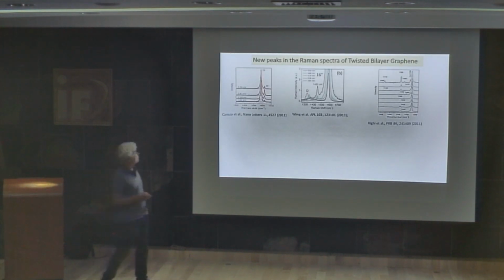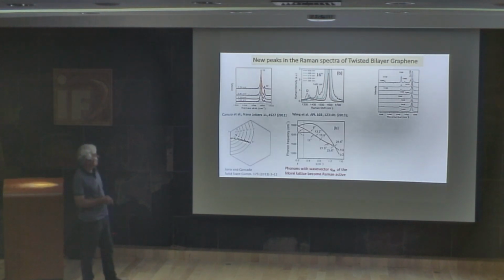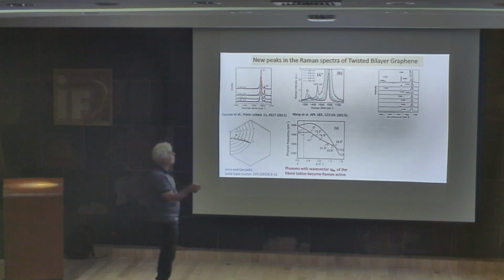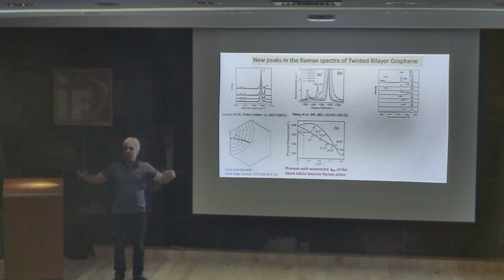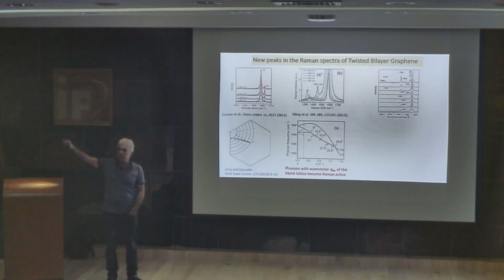And another important work that was done, and there is Jessica Campos who worked on this problem, was new peaks that appear in the Raman spectrum of twisted bilayer graphene. The point is that when I have the superstructure, the reduced Brillouin zone is small. Then I have new peaks that appear because the peaks that were in the interior of the Brillouin zone are folded to the center of the Brillouin zone when I have the superstructure. And those peaks are related to the fact that we have this moiré pattern.